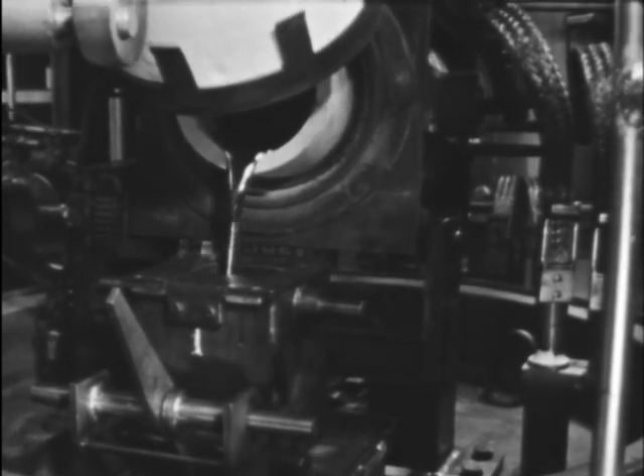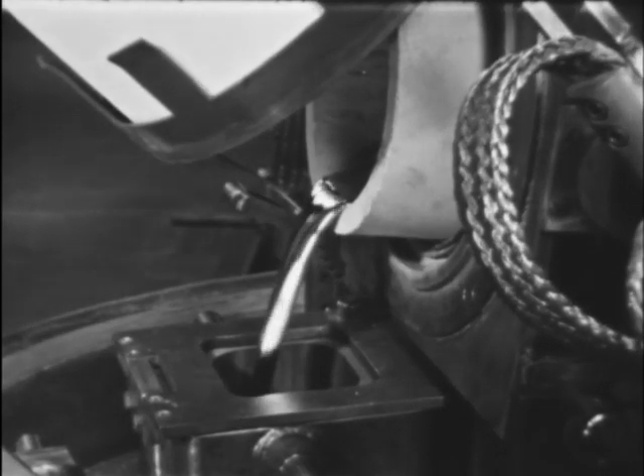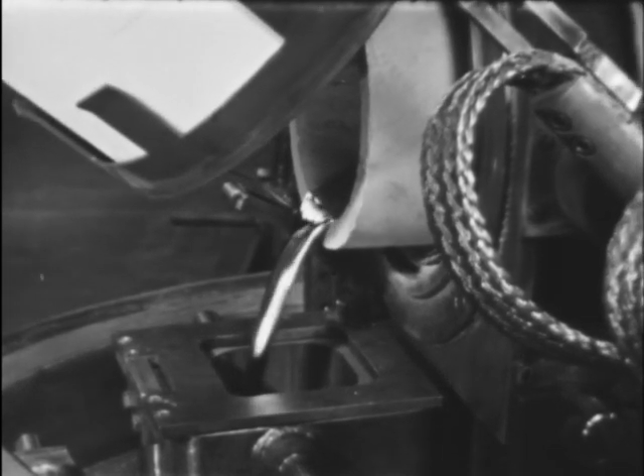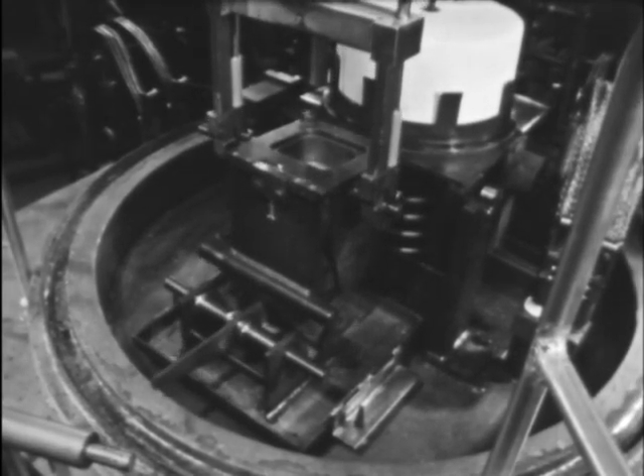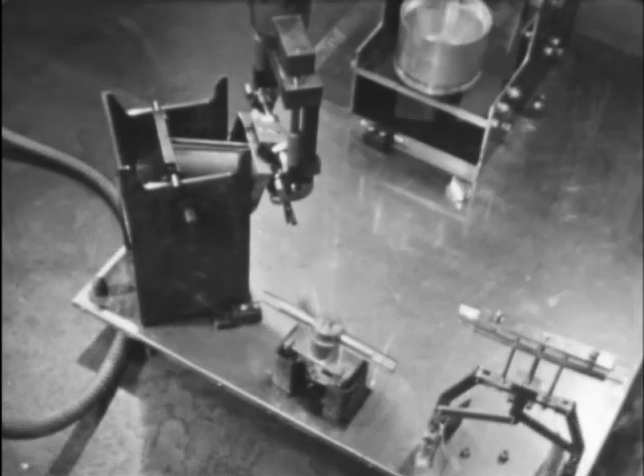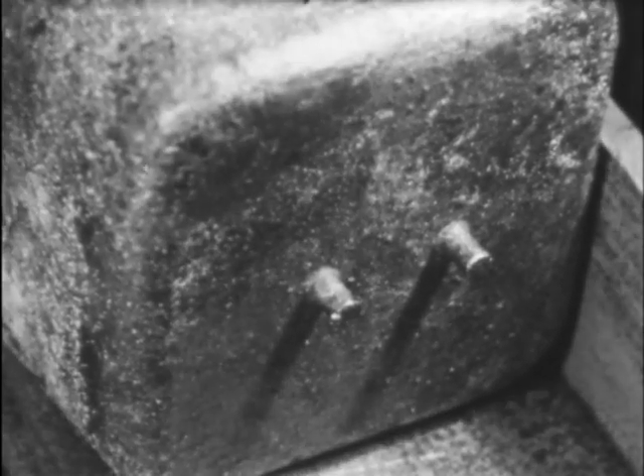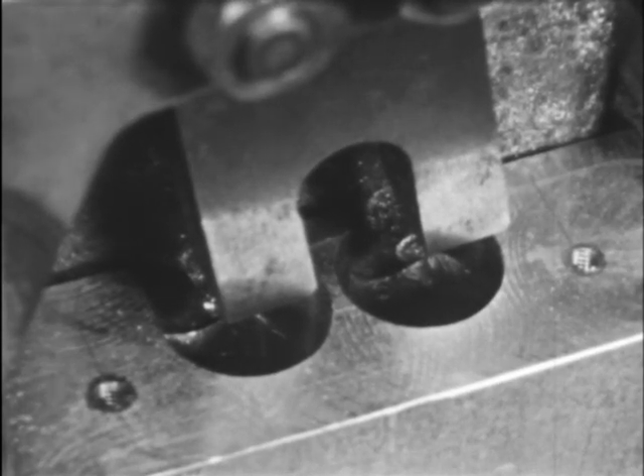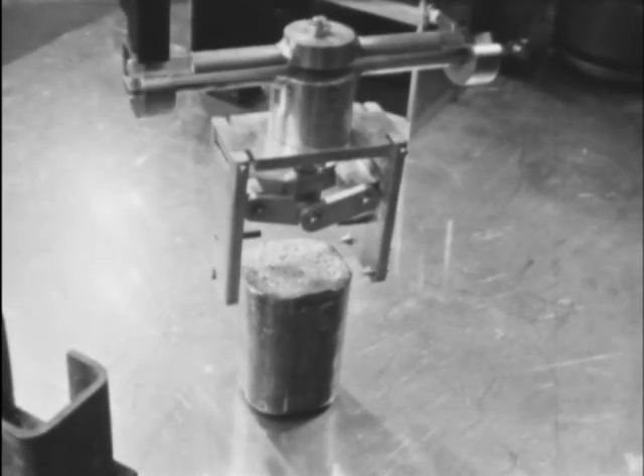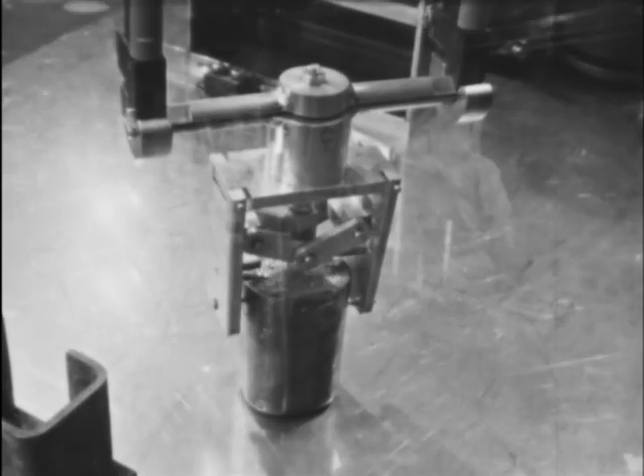Refined fuel is poured from beneath the slag and is cast in an unheated mold. The projections on the bottom of the ingot are sheared to provide samples for analysis. Reprocessing of the spent fuel is complete and the ingot becomes the starting material for refabrication.